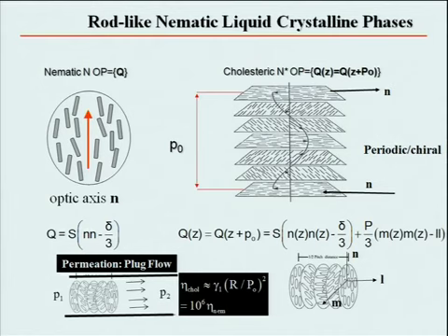And working out the physics of this effect is very interesting. As the material flows, this is steady state. So the only dissipation is as you move, if you're a director and you move, you're rotating, so that at this station you are vertical, and at this station you are horizontal. So we have steady state. So the only corotational derivative that we have in the system is the velocity dotted with the gradient of the orientation.